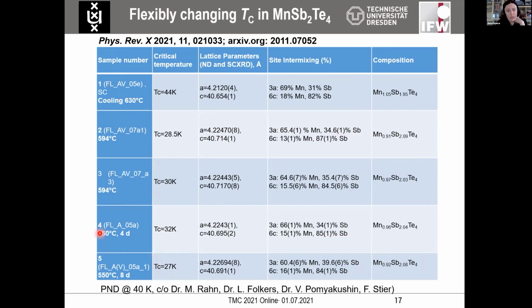If we look at samples that are obtained at the same temperature, but are annealed with different duration, we observe increasing disorder. So if we first had more manganese in the central position and less manganese in the outer one, if the sample is annealed a little longer, it starts to become different. Nevertheless, we always observe slight sub-stoichiometry of the samples. Even if we produce them at higher temperatures, there is still quite noticeable sub-stoichiometry of manganese. And all these temperatures tend to cluster at around 27 or 30 K.